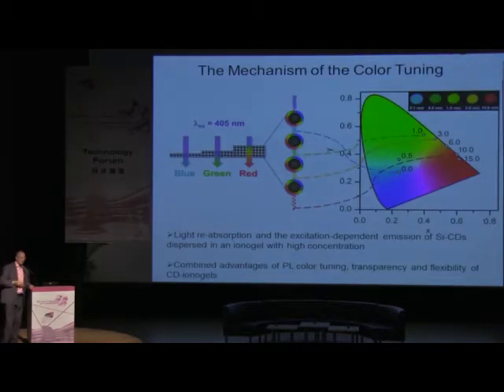So why is it like that? This is a direct consequence of two factors: the high concentration of carbon dots in the ionogels, and the fact that the emission depends on the excitation wavelengths. Here you can see real color images taken when we excite thinner blocks, then they emit blue light. If you go for thicker blocks, like 10 microns, they are definitely red. And every color in between is possible.